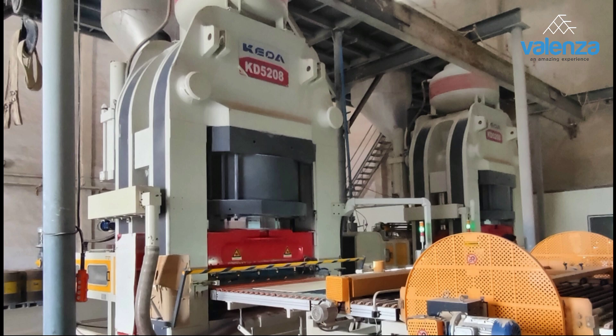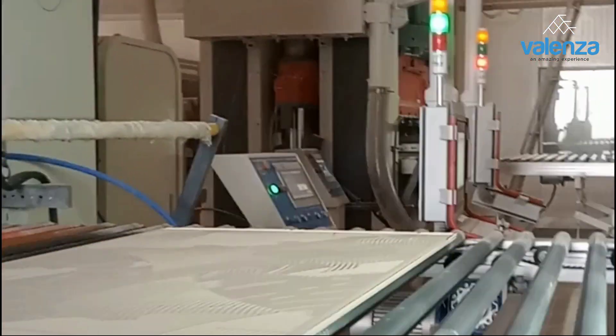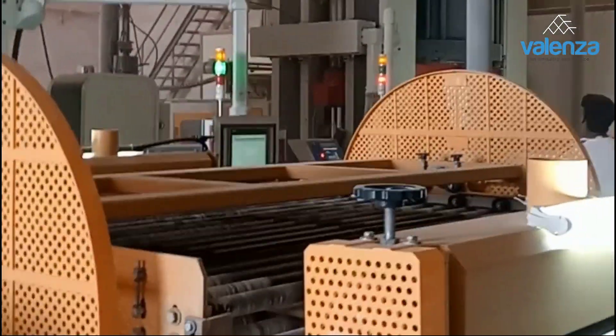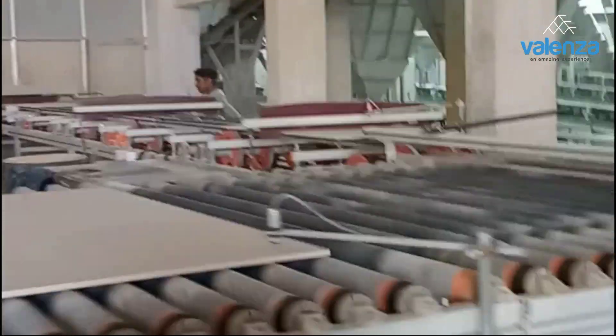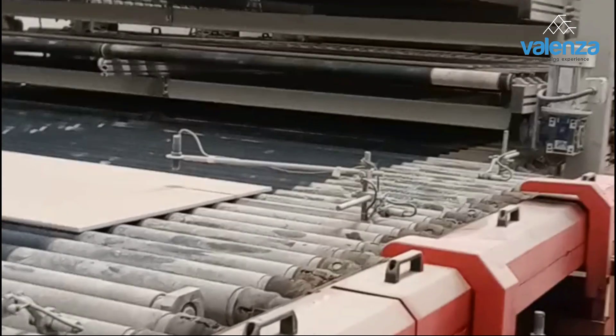The mixture of powder travels through the conveyor belt to the press machine. Next, the clay is pressed or formed into a tile shape. This tile's base goes directly to the firing pre-heating kiln. Through this step, the tile gets enough strength to prevent it from breaking during the glazing and printing.